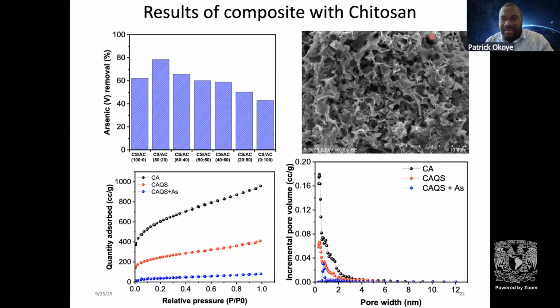But then something fascinating happened. Here is our carbon, here is carbon with the chitosan composite, and here is carbon with the chitosan composite plus adsorbed arsenic. Here you could evidently see that the amount of nitrogen adsorbed is lower in this part and even far lower in this part. This shows that putting chitosan in this carbon actually disrupted the surface area and blocked some of the pores that we have, and eventually we have lower pores.